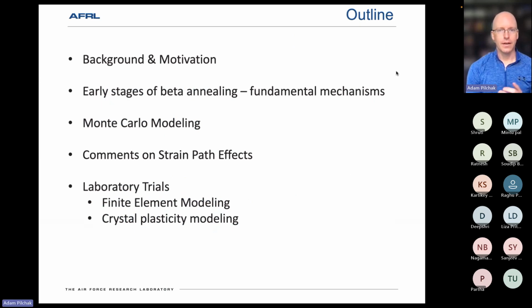So just a brief outline, right? I'll cover a little bit of the background motivation, talk about what happens when you go from, say, the two-phase field, and in the very earliest stages of dissolving that secondary phase that's pinning the grain boundaries, what happens to the underlying beta phase structure. And then we will look at some Monte Carlo modeling approaches that were used to try to understand some of the sources for the abnormal grain growth.